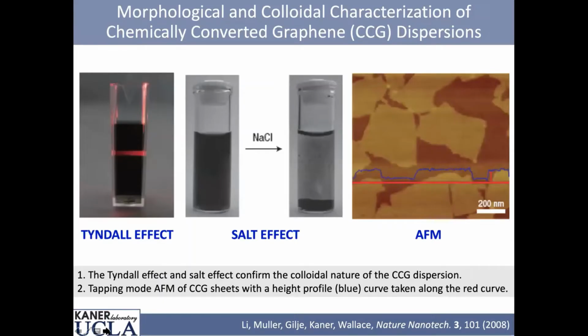So first, a little bit more about graphite oxide. The first thing we did is we reduced it chemically. We just used hydrazine. And so this is chemically reduced graphene oxide. It disperses in water. And I call it a dispersion, not a solution, because it shows the Tyndall effect. The Tyndall effect is if you take a laser, in this case, we're taking a red laser. If this were a solution, the laser would go right through and you wouldn't see any laser light.